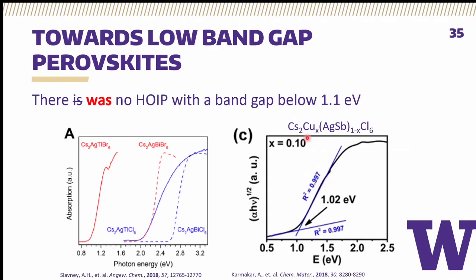Oftentimes in these crystals, in these perovskite materials, when you have a dopant that is responsible for a significant amount of band gap reduction, it's hard to tell if that is due to true electronic band gap reduction or just a reduction in the apparent optical band gap, because of spin relaxation due to spin orbit coupling or parity relaxation or some other quantum mechanic effect. These dopants can actually have optically active defect bands that contribute significantly to